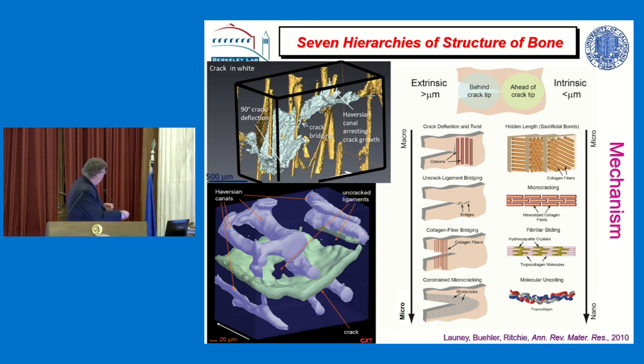This is also looking at it in three dimensions. This is a bone crack, that white region is a bone crack. That's the front of the crack. These regions here are the Haversian canals, and anything dark blue is unbroken. And you can see, even though there's a crack here, there are regions of unbroken material. And that unbroken material acts like a bridge. It's like a bit of toffee in your mouth, basically, it makes it more difficult for the crack to open. These don't seem very scientific, I must say, but they're very, very potent. The length scales are quite coarse, but they're extraordinarily potent mechanisms of generating resistance to fracture.